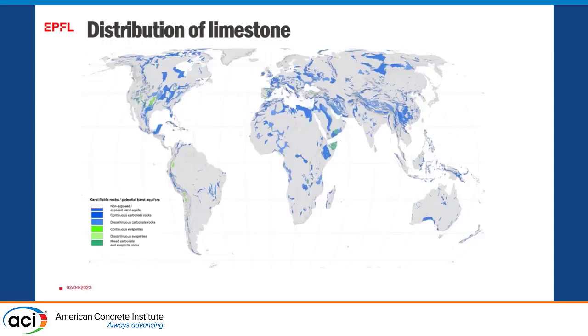And more important than that, we actually face quite a problem in many parts of the world because we have these 2 regions where Portland cement was developed nearly 200 years ago, where we see that the limestone deposits are very nicely interspersed with clay deposits. Now, when we go to places like Africa, we've got a problem because we see these limestone deposits are very sparse. And that means many countries in Africa can't produce clinker. They have to import clinker.